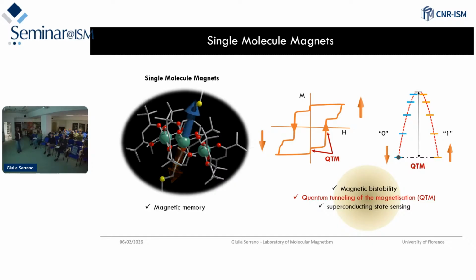Then this is also a quantum object. So we can observe these jumps in the hysteresis loop that correspond to the quantum tunneling event, in which at some resonant fields, like 0 or other resonant fields that depend strictly on the kind of molecule, we can have a tunneling of the electrons from one magnetic state, the down state for example, to the up state. So we lose this fixed magnetization behavior, and we start a resonant tunneling regime. And it's important to understand that because this is the key of the sensing of this molecule to the superconducting state. This is the topic that I mostly investigated.